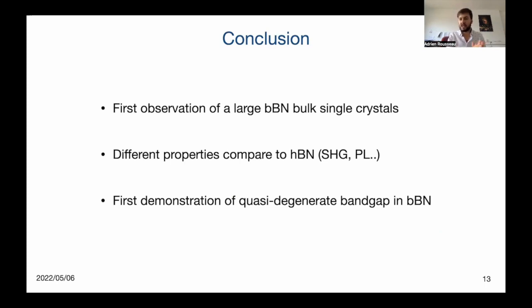To conclude this presentation, we performed the first observation of a large Bernal boron nitride bulk single crystal by combining second harmonic generation and photoluminescence microscopy. We then observe different properties compared to hexagonal boron nitride, where the Bernal boron nitride shows strong second harmonic generation and a strong luminescence peak at 6.035 electron volt, which could be a very interesting material for future optoelectronics applications.